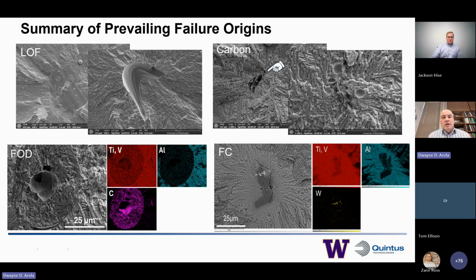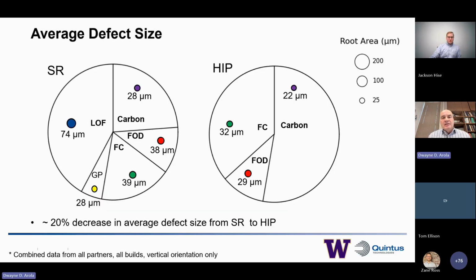So I'd like to point out, first of all, average defect size, understanding those categories. Here we're using some pie charts to represent those four categories. And I'm going to break out the voids for the stress relief condition in this pie chart into two, so show you the percentage of the lack of fusion and the average Murakami dimension of that defect, and then gas pores, and then three remaining categories: foreign contaminants, foreign object debris, and carbon defects. You can see that the voids contribute almost 50% to the total number of defects which contributed to fatigue failure.